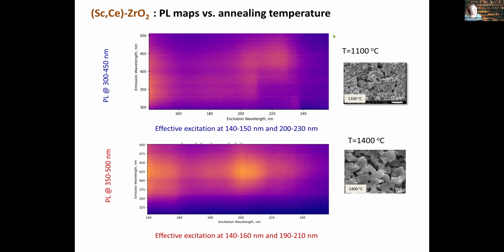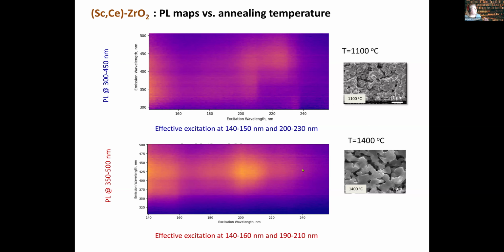So there were 2 questions: what to do with such variation of photoluminescence at different excitation wavelengths, and how to control it. Thank you for the development of luminescent mapping at the P66 line. And this July, we took exactly these good maps. In these maps, the horizontal direction shows variation of excitation wavelengths from 140 nanometers up to 250 nanometers, and the vertical direction shows variation of photoluminescence wavelengths from 300 to 500 nanometers. These 2 maps are plotted in nearly the same way, and the intensity scale bar is the same for all of them.